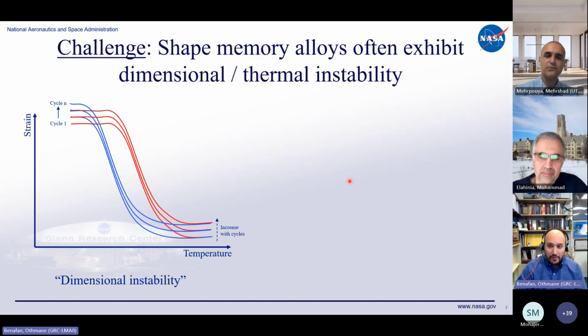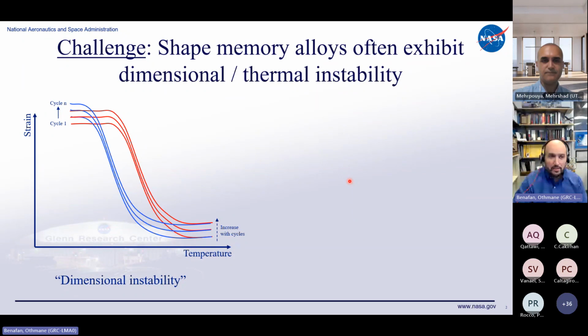Just a recap, I assume everyone is already aware of shape memory alloys, but I'll recap quickly the type of challenges that we typically see in shape memory alloys. One of them is dimensional instability. For example, when you take a cartoon of strain as a function of temperature and you heat and cool under some stress, there is a residual strain that develops because the alloy is not dimensionally stable. This is something you will see in an actuation response, for instance.